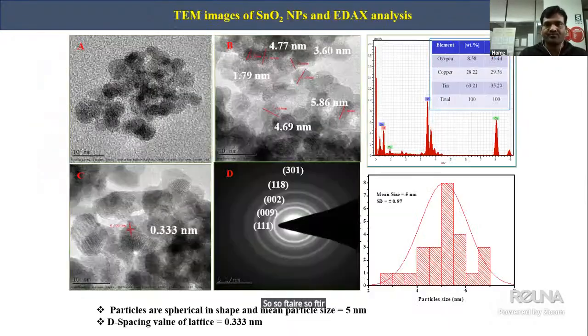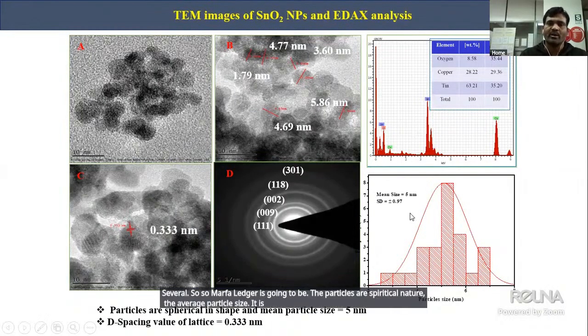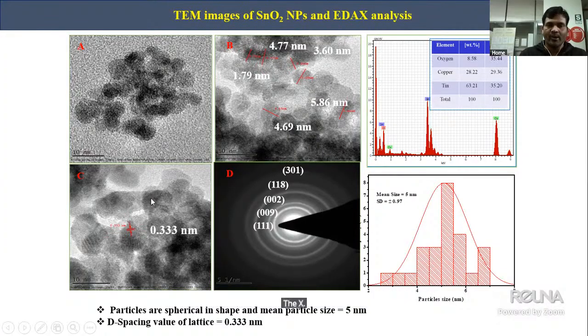Further, the tin oxide material is confirmed by TEM analysis. TEM analysis gives the information on morphology, so the size and shape of the material are confirmed. The morphology shows the particles are spherical in nature. The average particle size matches exactly with the XRD result. Here the d-spacing is calculated, and the interplanar distance of the plane is identified, which is in good agreement with the XRD result.